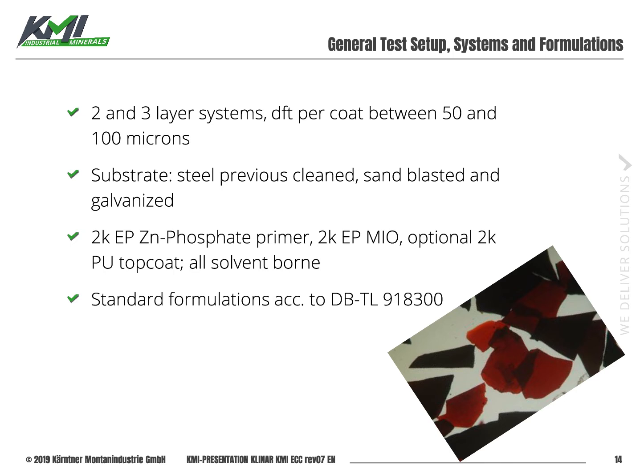A few words about the test setup, the systems and formulations we used. We always tested the 2 and 3 layer systems with dry film thicknesses per coat between 50 and 100 microns. The substrate was always steel, sometimes just cleaned, but also sandblasted or galvanized. We always had a 2K epoxy zinc phosphate primer, which is a typical product available on the market. Then we had a 2K epoxy MIO coat where we played around, and optionally we also had a 2K polyurethane top coat in the test series, and all of them were solvent based.